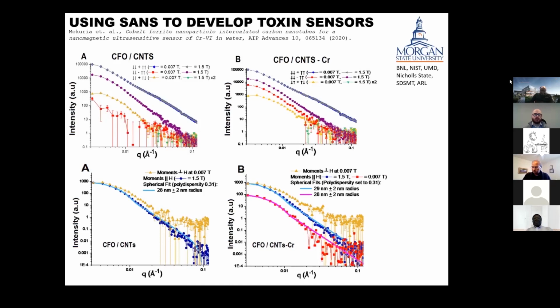But these are polarized SANS results that I show on this slide, and they show that the magnetization enhancement is not due to the nanoparticle length scales, so it's not a local enhancement of the magnetism, but it's actually attributed likely to longer range clusters of the nanoparticles. And this is shown in the top plots. These are intensity, so these are scattered neutrons as a function of direction as they're scattered from the sample. And that first point about the magnetization is shown in the upper two plots. Just looking at the ratio of those two upper curves, they're basically unchanged. And so what the researchers can extract from that is that there's no local enhancement of the magnetization.